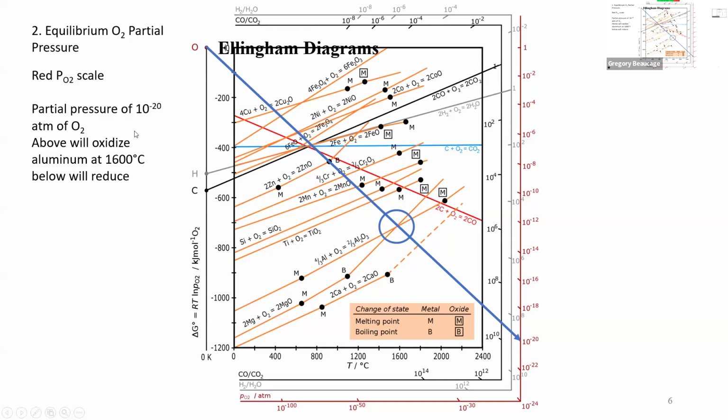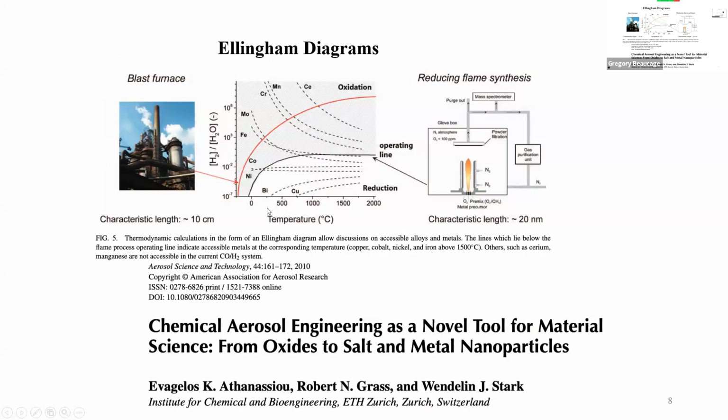Like if you wanted to make, so this is a pyrolytic synthesis, and you're trying to make a ground state metal from it, right? Of all the metals that you can look at, which ones could you possibly make? Normally, when you burn something, you make an oxide. Like you burn ferrocene, you're going to make iron oxide. You can't make iron because oxygen oxidizes it, right? But there are some conditions. If you have a reducing flame, it's possible you can just burn and make ground state metal.